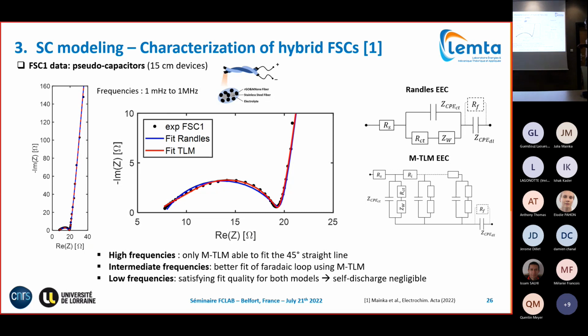Concerning our depressed semi-circle at intermediate frequencies, associated with electrochemical charge storage, once again we have better fitting quality with our TLM rather than with the Randles circuit. This means we conclude that the TLM circuit is more appropriate to model this charge storage contribution for these devices.